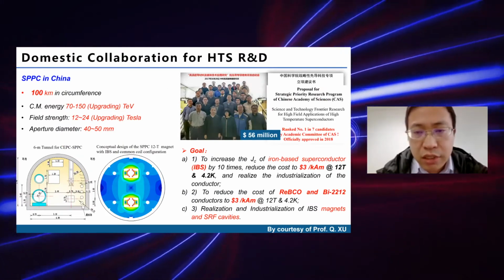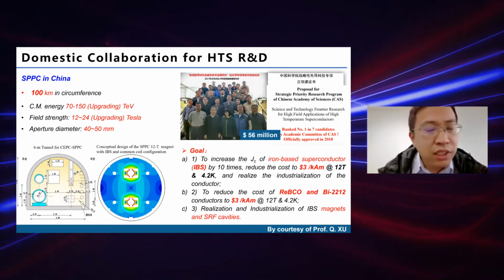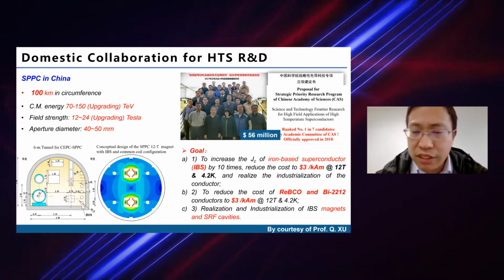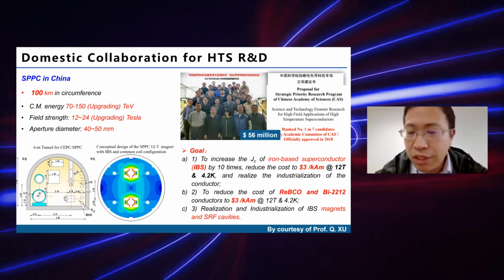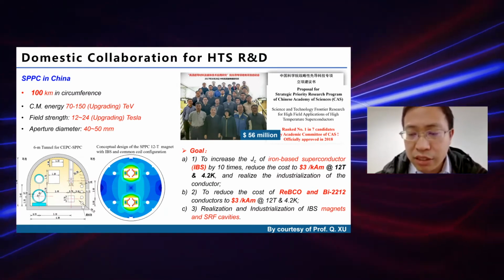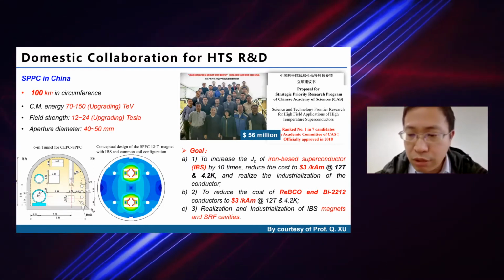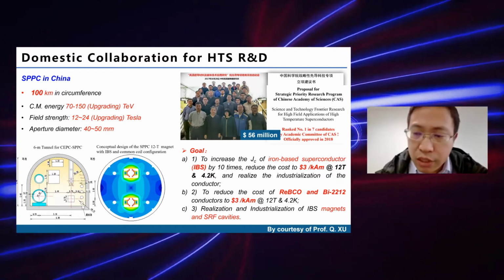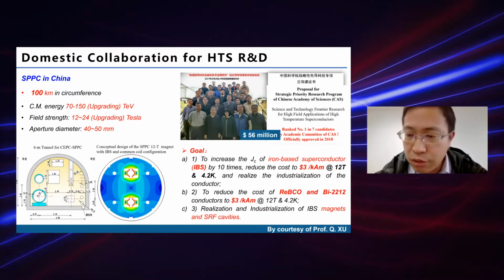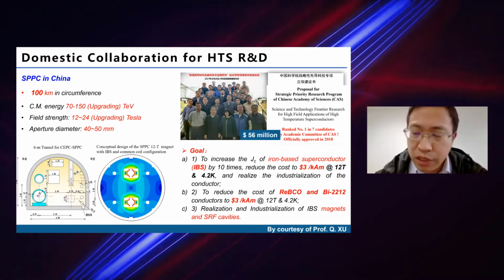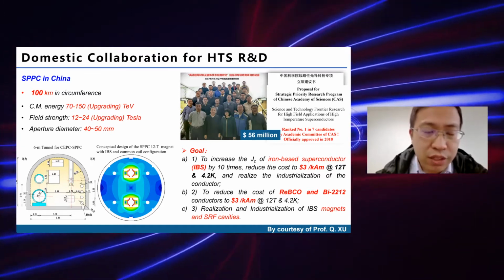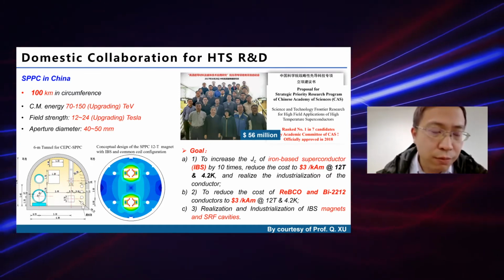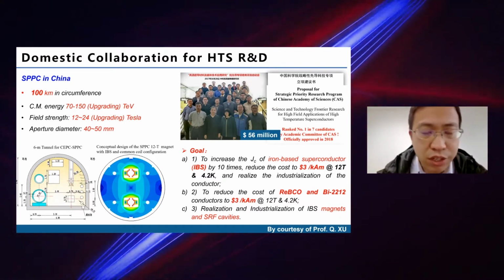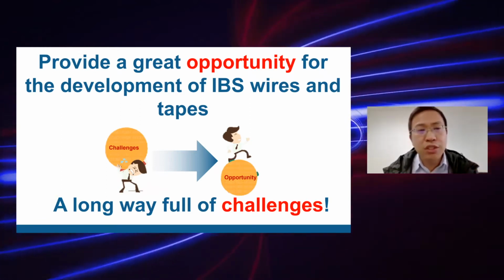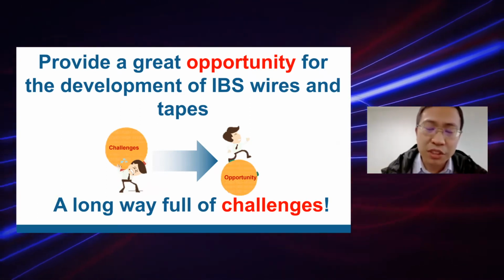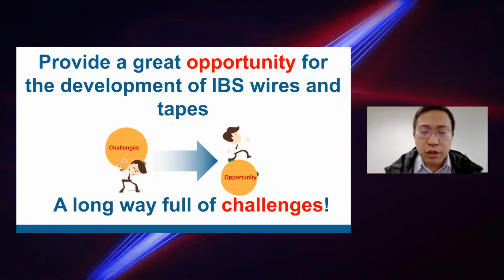Due to the very good performance of iron-based superconductors, the Chinese government has invested about $56 million to increase the critical current density of iron-based superconductors, and of course, also Bi2212, and decrease their cost to $3 per kiloampere meter. The best one will be used in the next generation accelerators, SPPC, which will maybe be developed in China. So this is a great opportunity for the development of iron-based superconducting wires and tapes. And of course, it's a very long way full of challenges.